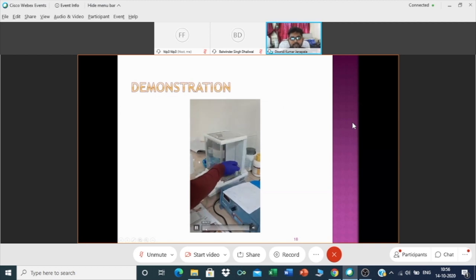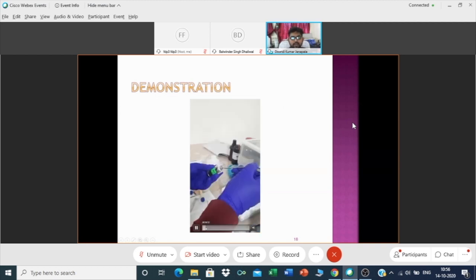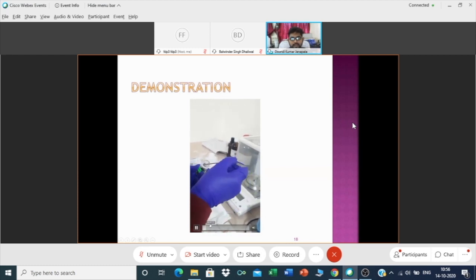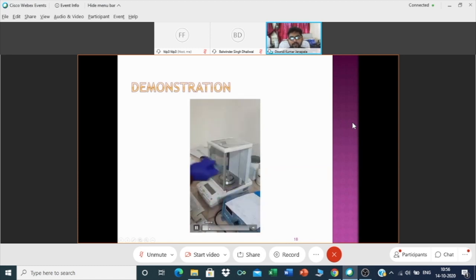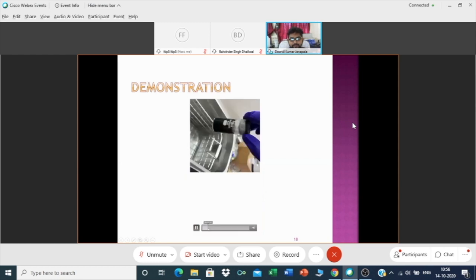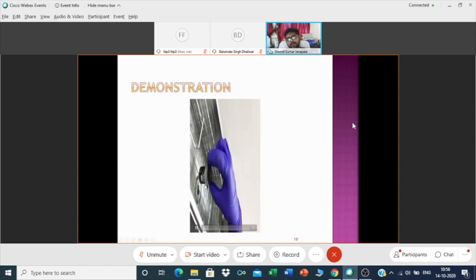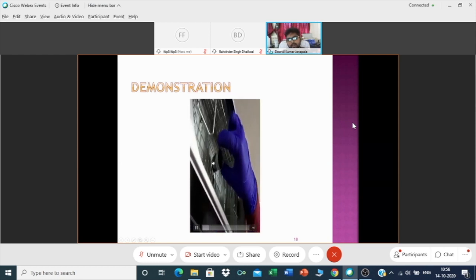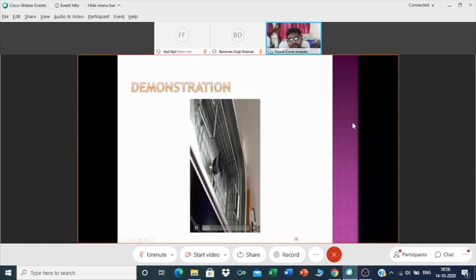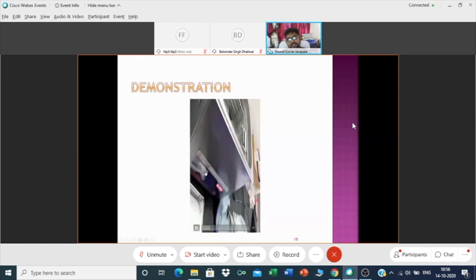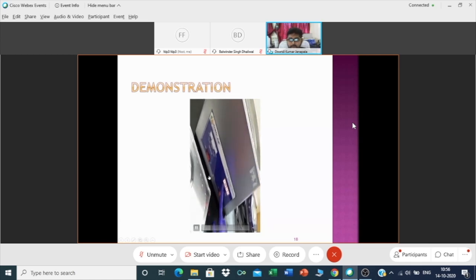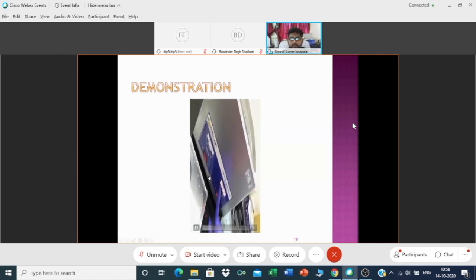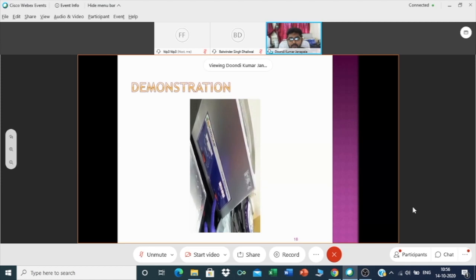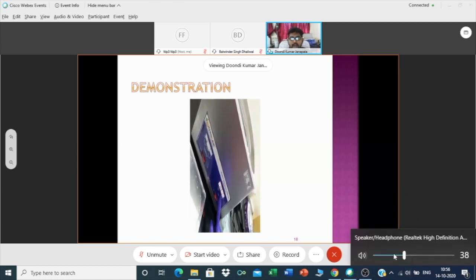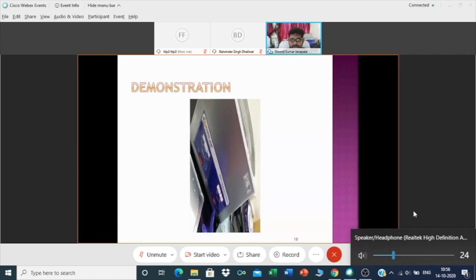First, I will take a weight ratio of my particular GO, the GO that I made. After grinding it, I will take that particular one. After that, I mix it with a little bit of deionized water, a drop, and ethanol. I added a little bit, and I put that beaker in this particular equipment. This is called ultrasonication. Your polymer uniformness will depend on how well your GO particles are dispersed into the solution you took.